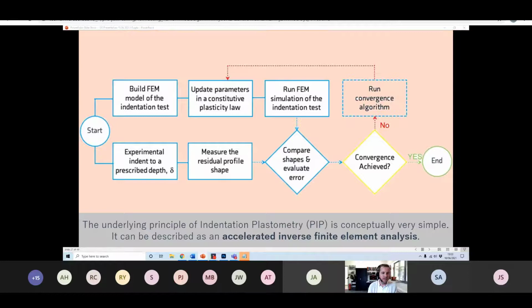If you are interested, not everyone is, but I'll present it nonetheless, what that algorithm looks like is conceptually very, very simple. The process involves conducting the experiment and measuring the residual profile shape. What we then do is run an equivalent indentation finite element simulation, and in that model we have to specify some constitutive plasticity equation, and we can then iteratively adjust the free and unknown parameters in that equation until the measured and predicted profile shapes converge. And while we do this, we monitor the goodness of fit between measured and predicted data, and our objective, or the objective of our software, is to minimize this difference.